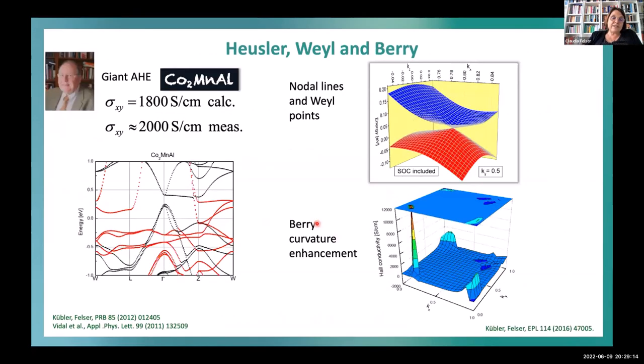But I remembered that Jürgen Kübler and I had already been working for a long time on the electronic structure of the Heusler compounds. And we were looking also for something very strange. This is the so-called Berry curvature. We were looking for this because people in spintronics like the anomalous Hall effect. This is a more classical counterpart to the quantum anomalous Hall effect. So we measure simply the Hall effect in a magnetic material, and we get an additional contribution, which I show in a moment. And this comes from the magnetism.